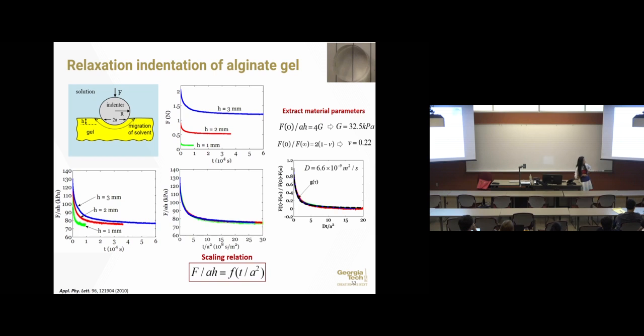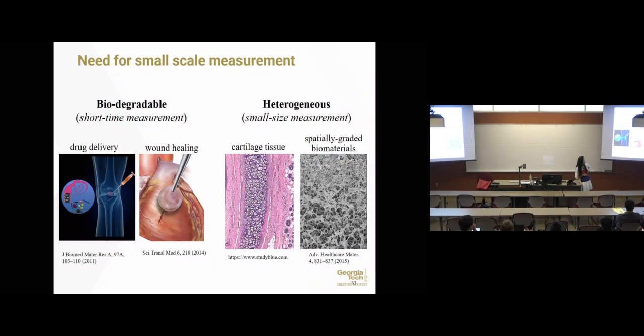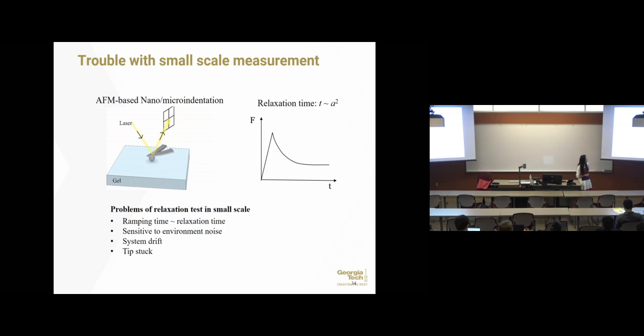And using our method, we can easily extract the poroelastic properties. So here, I just want to say that the method worked very well. We use it to test many different gels. But later, when I became an independent PI, I wanted to apply it at smaller scale for biomedical applications. And the reason is because a lot of these biomaterials have natural inhomogeneity. You have to probe the local properties using small size. And for the other, a lot of the materials are time sensitive. So if you have a smaller size of indentation, the relaxation time is much shorter, so you can finish the test much faster.